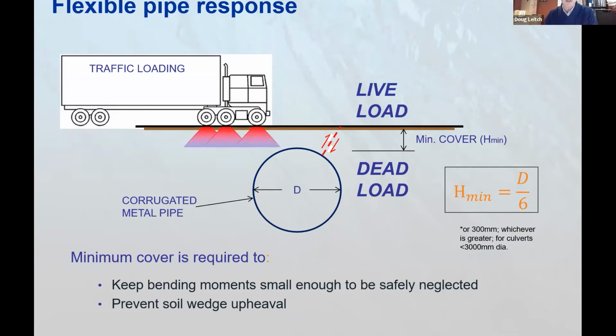And secondly, it prevents what's called soil wedge upheaval. And by soil wedge upheaval, you can see this area right here and this area at the 1 o'clock position. When the load approaches, there's a tendency to push that cover back up. So pipe has to be buried deep enough to withstand that. Typically, and this isn't always the case, the important part is the height of cover, and that may typically be diameter divided by 6. That's a very common way of considering it.